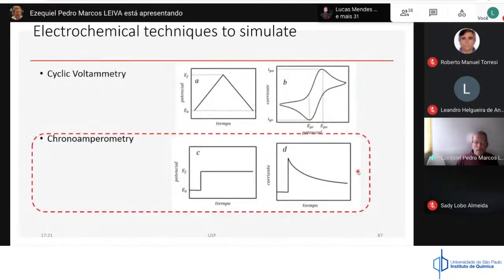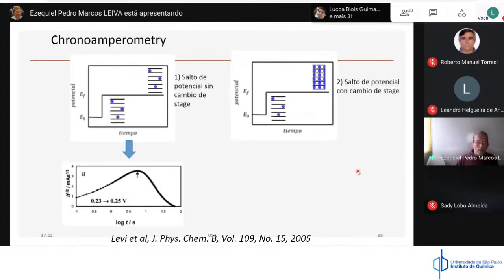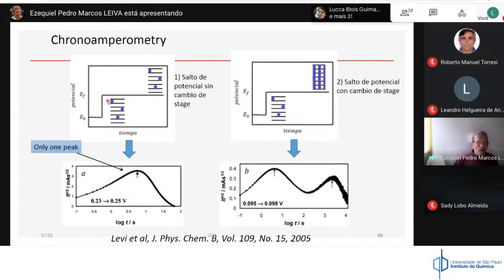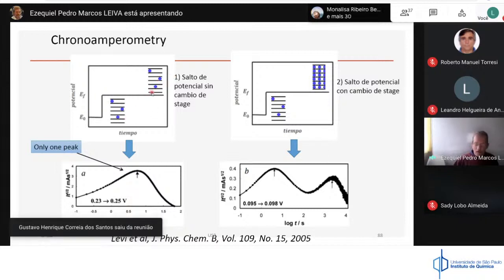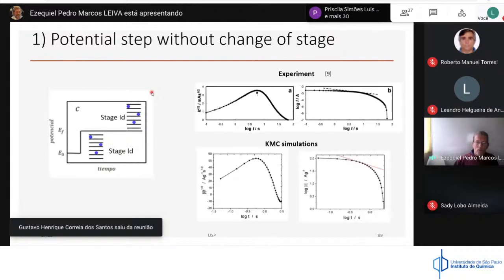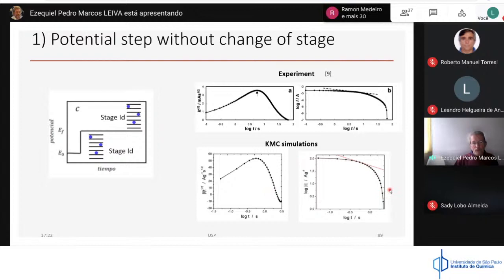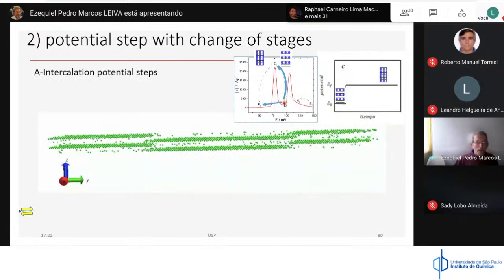You can also make chronoamperometry, and there we developed a number of simulations where you can simulate a potential step, and with this potential step, you can study the transition between the same stage or between different stages. Experimentally, the representation of the current as a function of time shows one maximum or two maxima, depending on the transition between different stages, as you can see here. And of course, we made the simulations, the upper is the experimental curve, the lower is the kinetic Monte Carlo simulation, and we found results very close to the experimental results. This is, for instance, a step from E3 to E5, that is from phase 2 to phase 1 of graphite, and this is the simulation.